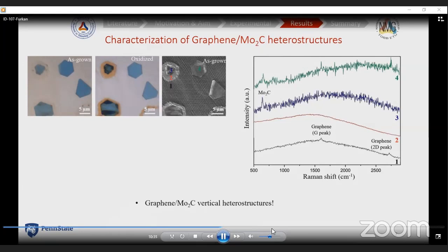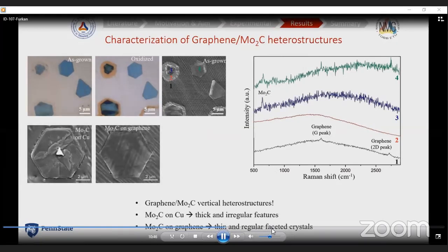So therefore, two different crystals are formed. One of them is on copper, the other is on graphene. And similar to the literature, the molybdenum carbide on graphene is thinner, and also it has regular facets. So since this is an already reported result in the literature, as I showed you before, I'll not be talking about this in detail.